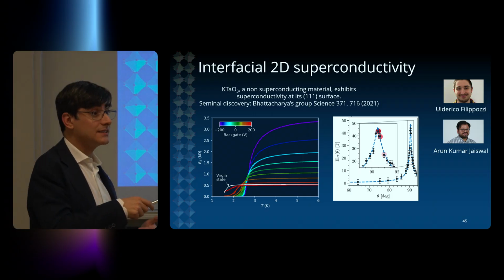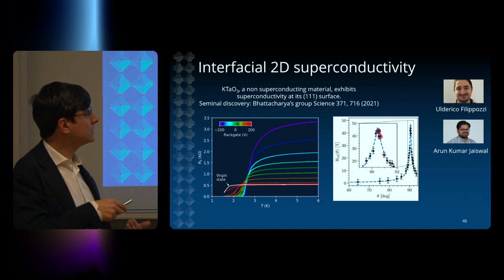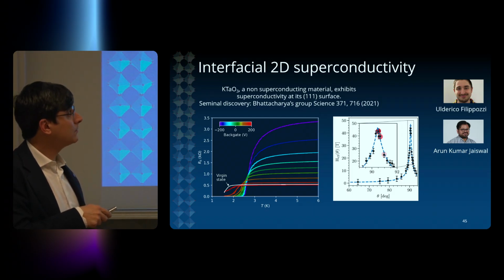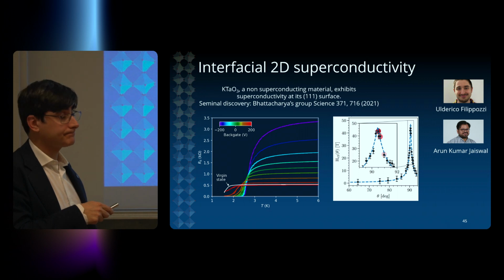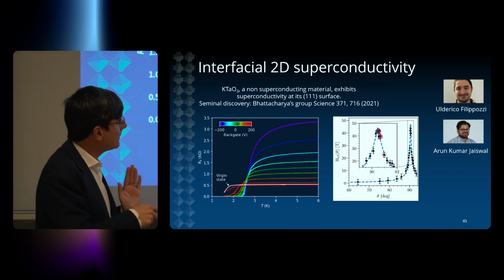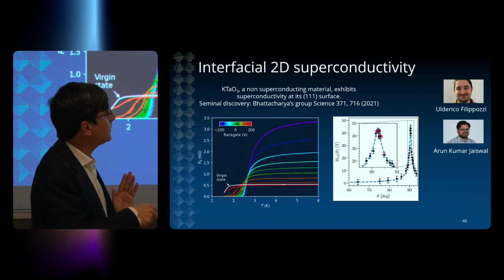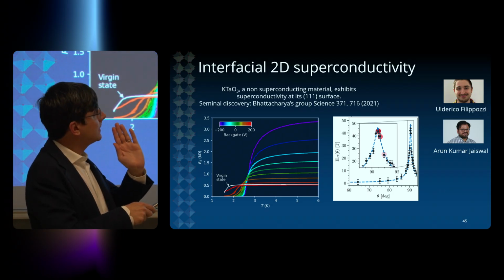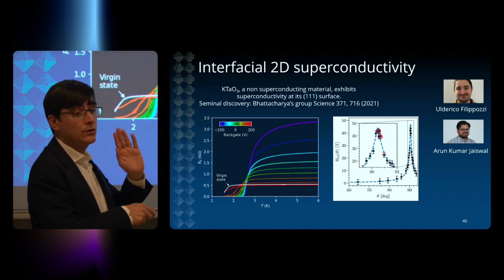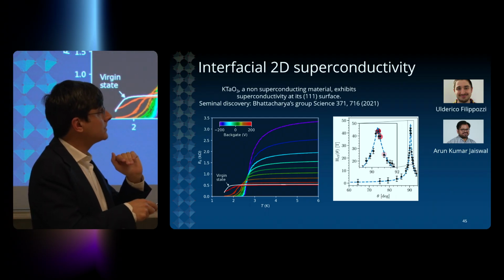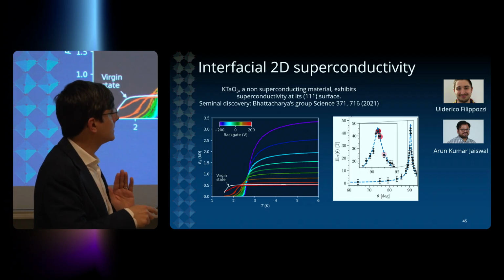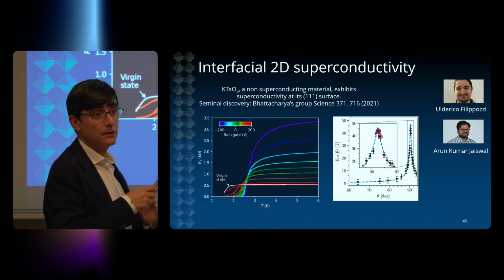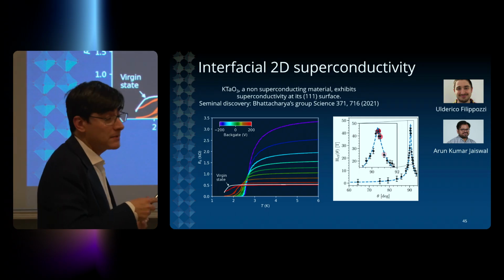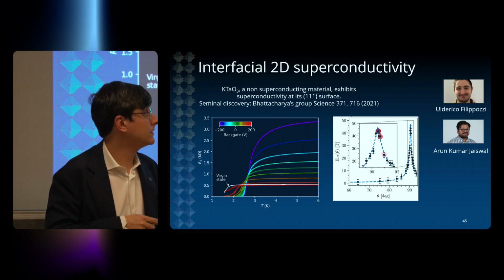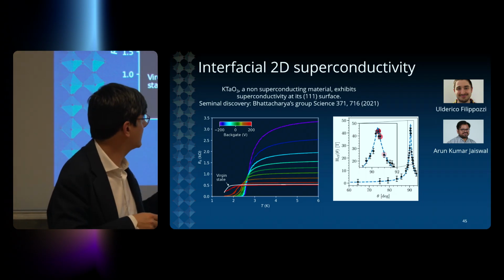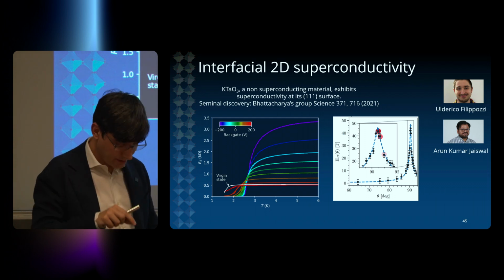This material is extremely resilient to magnetic fields. This superconducting state can survive up to magnetic fields approaching 50 Tesla. In order to have this extreme resilience, you need your magnetic field to be perfectly parallel to the interface. As soon as you move a little bit from the perfect orientation of your field, your critical field decreases in this V-shaped curve. So this is an extremely resilient superconductor with a pairing mechanism between the electrons that is still not fully understood, which is something that can only be realized at these oxide interfaces.